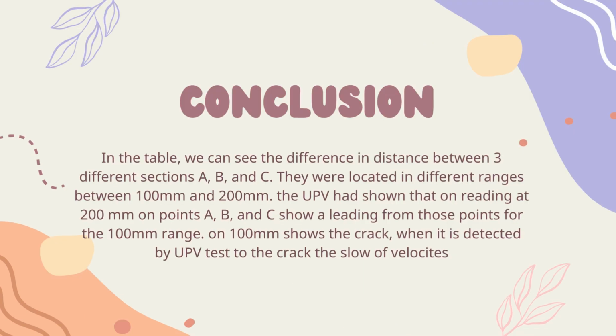For the conclusion, in the table we can see the difference in distance between three different sections A, B, and C. They were located in different ranges between 100 millimeter and 200 millimeter. The UPV showed that the readings at 200 millimeter on points A, B, and C showed a leading from those points for the 100 millimeter range. At 100 millimeter, a crack is detected by the UPV test, shown by the slow velocity.